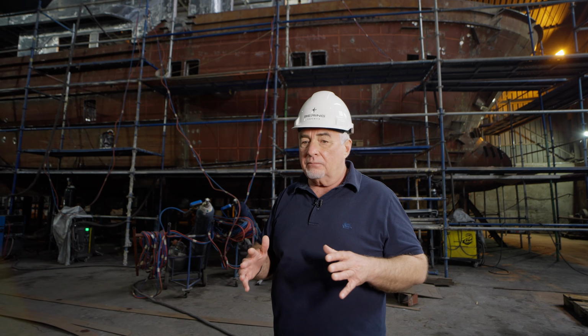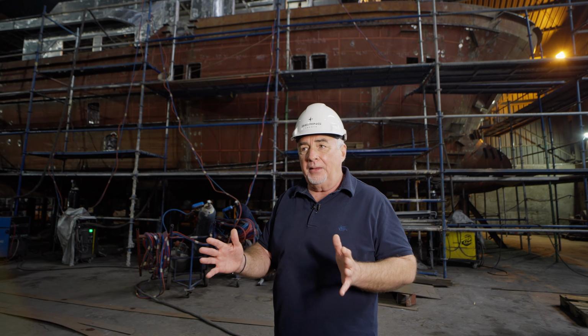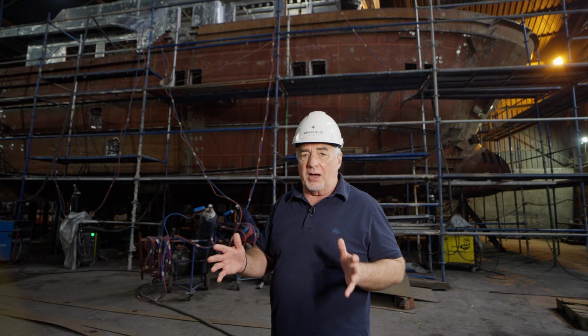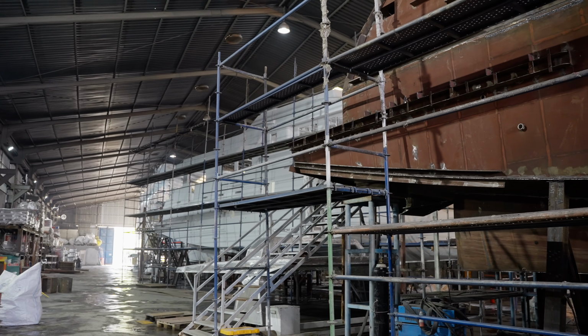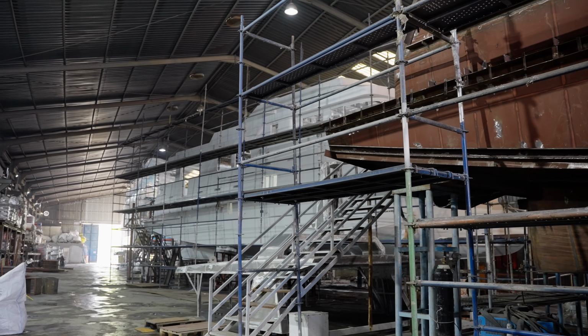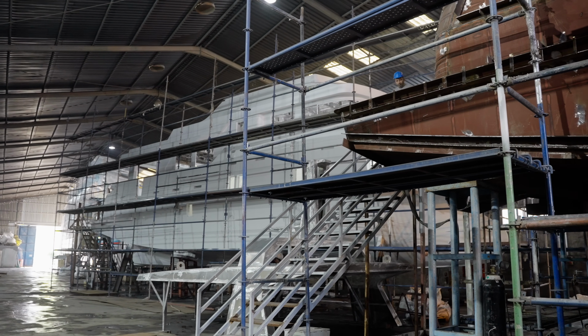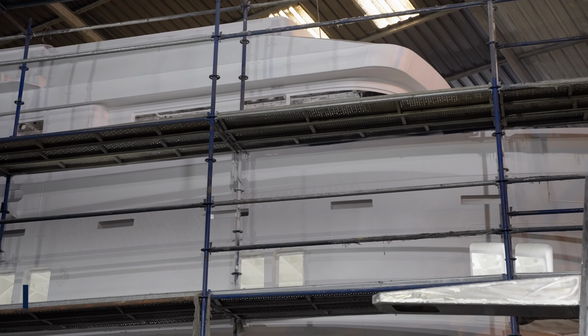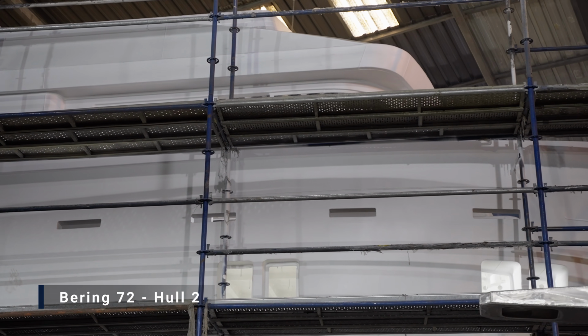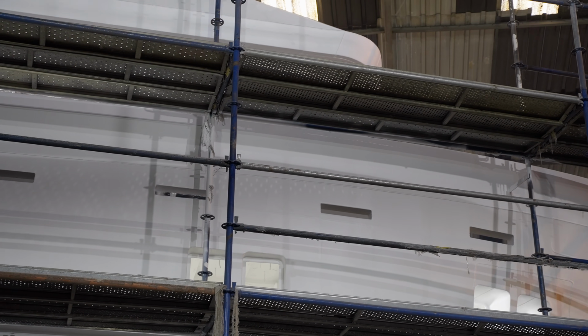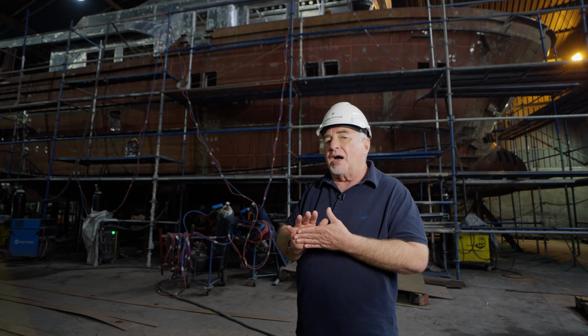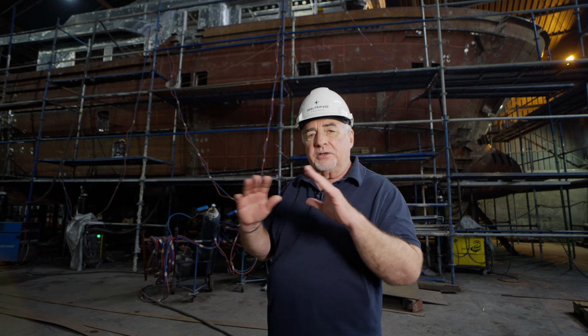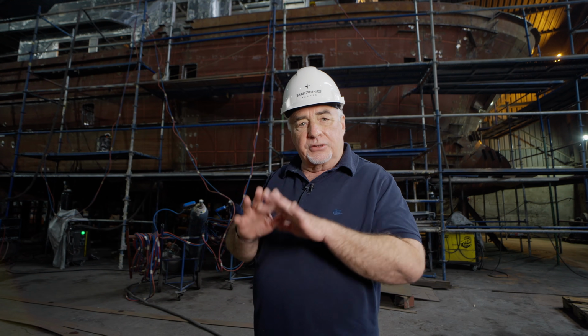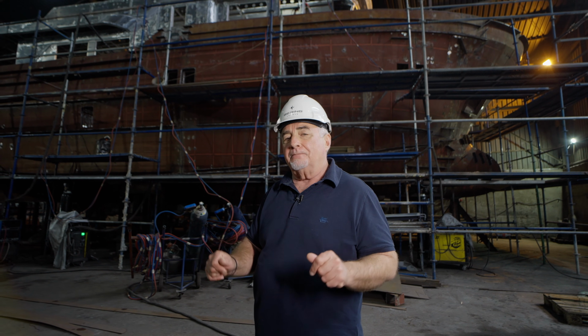After sandblasting, in a short period of time, we need to apply protective primer. You can see a very big difference between the cleaned parts around seams. You can see it's very, very clean and shiny, almost like stainless steel. When the metal is in this condition, we apply protective primer. We have to be absolutely sure there is no rust and no leftovers of the sandblasting. So we need to thoroughly clean it after sandblasting and then apply protective primer.